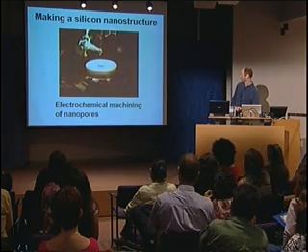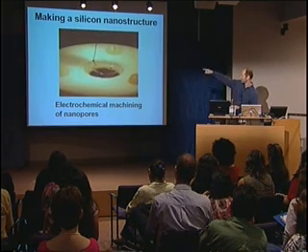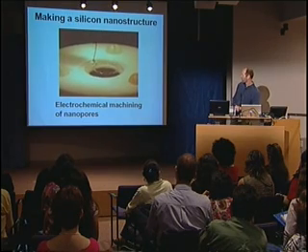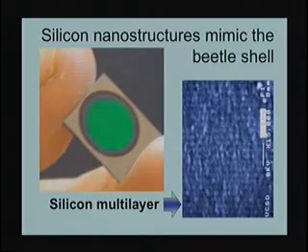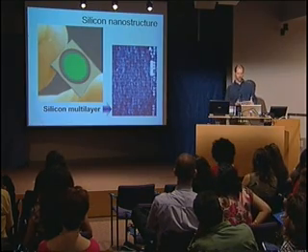And what's going on in that little experiment there is there's a silicon wafer, and those bubbles forming are a corrosion reaction that we're turning on with this electricity, with this wire loop that you see there. And that is drilling out very small holes, nanometer scale holes in this silicon wafer that generated that little chip. And when you're all done, you get a structure that has very fine layers to it. You can kind of see the layers in this picture here. This is a cross-sectional image of one of these little colored chips. And it has bands, a layered structure to it. And that layered structure gives you this green color that you see in that chip. And it seems really sophisticated and complicated, and you might wonder, well, what's going on here?